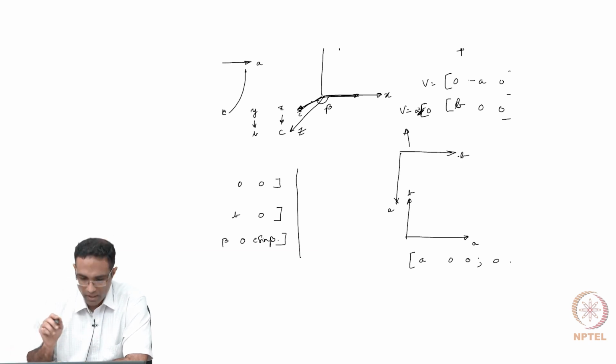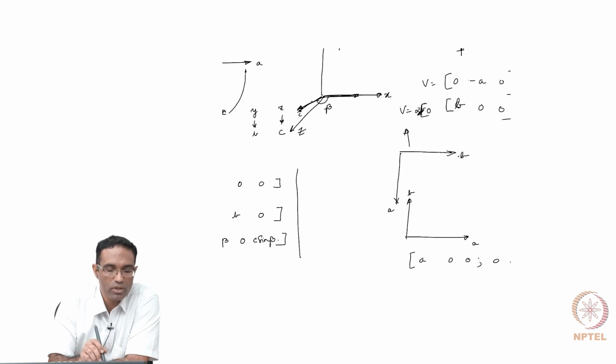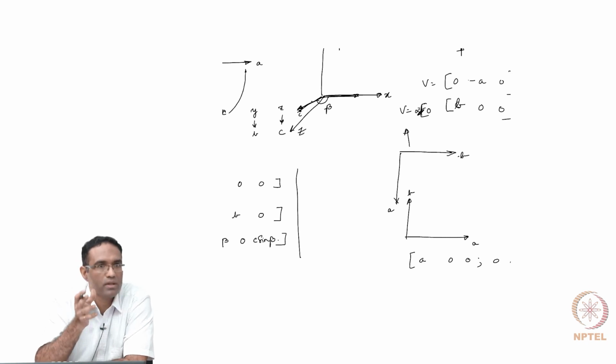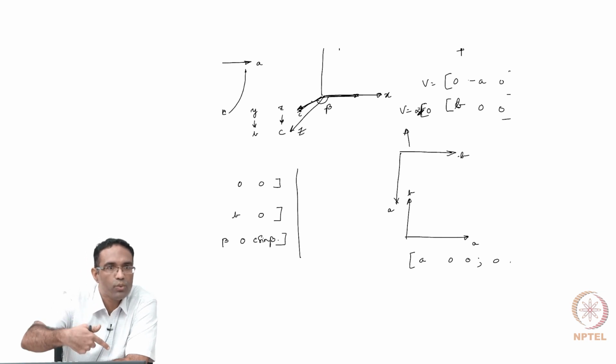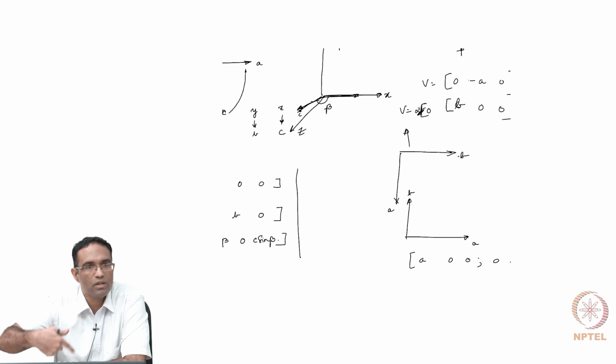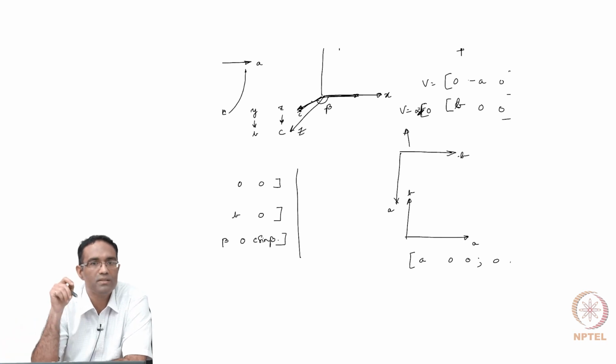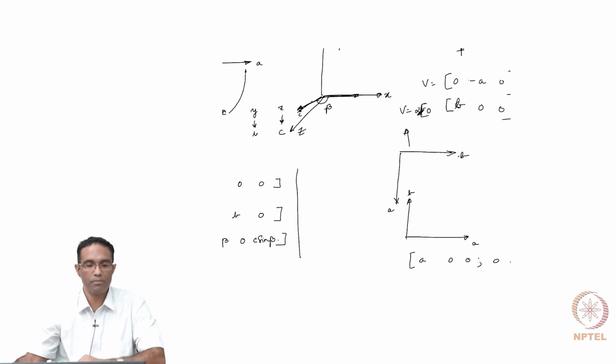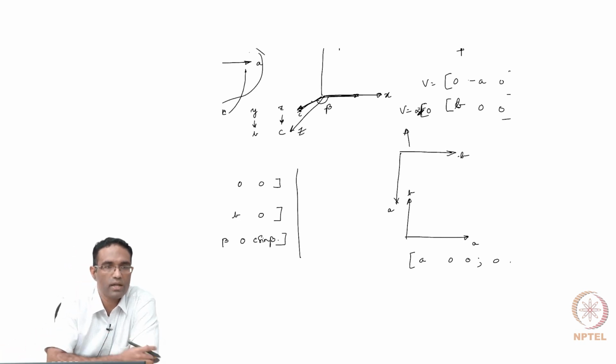In monoclinic systems, the fact that they have mentioned that we are looking at a unique B axis essentially means the B axis is what is pointing outside the board, and the oblique plane is the AC plane, not the AB plane. And this is important, right? You couldn't treat the C as a B, because then it would get mapped to the wrong basis fractional coordinates. So for this reason, it is important for us to keep track of how these lattice vectors are actually defined in the International Tables of Crystallography.